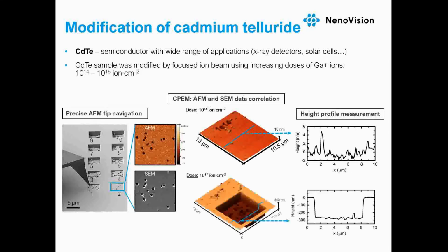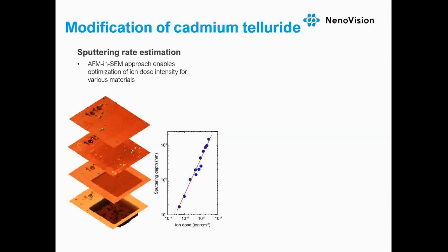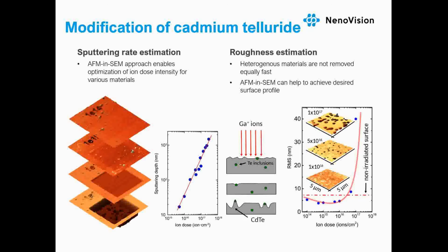First, LiteScope was used to precisely analyze the sputtering depth versus ion intensity to optimize the sputtering time. This characteristic can be done for any material and ion source. And because cadmium telluride represents a heterogeneous material, AFM roughness assessment was performed to achieve the desired surface profile.